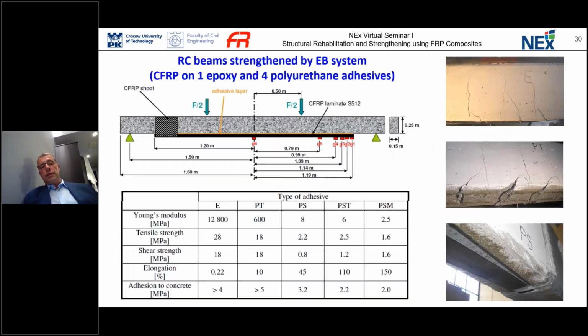Also, I would like to show you some examples of tests with not damaged reinforced concrete beams. In this case, with the same system, we used the same type of carbon fiber, but the only difference was epoxy resin in one case, and polyurethane adhesive layer on the other side. So you can compare the Young modulus of this system. Epoxy resin had 12,800 megapascal, polyurethane PT 600, PS 8, PST 6, and 2.5 megapascal.